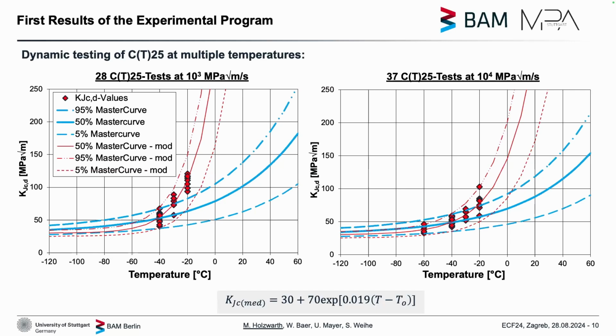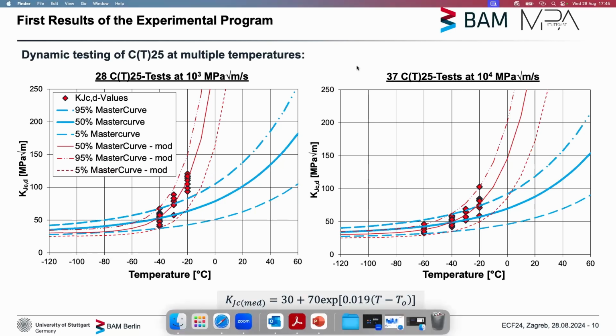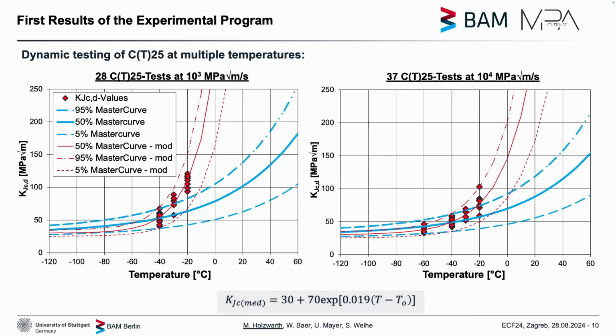Especially here, even the small scatter at minus 60 degrees still fits quite well into the tolerance bounds. Yeah, but we see it's still not yet perfect. So it's just one first modification attempt. It's to be expected. We see, for example, that here at minus 20 degree, the tolerance bounds are still quite conservative compared to the test results. For the faster loading rate, it's way better. And we also see at the slower loading rate, we have really high KJC dynamic values already at minus 20 degrees. While at the faster loading rate, this is not yet the case.